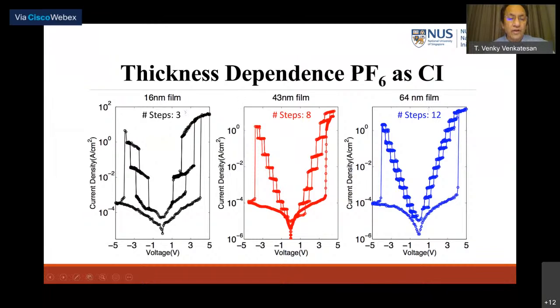What's going on is essentially the molecular diameter is 1.5 nanometers, and 3 sets of molecules are switching at the same time. Imagine this is a molecular system which I expected to be disordered, right? You expect it to be a disordered system because I just spun it on. For some reason, molecules are self-assembling, and as a result, you are switching 3 unit cells, and then the next 3 unit cells, and then the next 3 unit cells. So similarly, here, essentially 3, 3, 3, you're switching 3 layers of unit cells, which to me is amazingly remarkable.